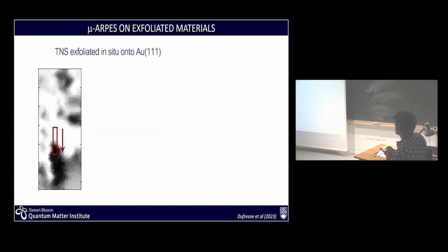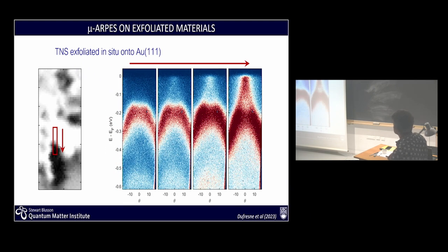This is a map of TNS exfoliated in situ on gold 111, and we do a scan over this trace. White means higher intensity, so thicker material. In black, you have basically the monolayer, and here is the evolution of the spectra. As you go down, you go from a well-defined valence band with a gap, about a 300 meV gap, as in the bulk. But as you go thinner and thinner and you reach the monolayer, all of a sudden the system becomes metallic. And so you're basically quenching that insulating state. And you're doing that through surface gating onto the gold surface.